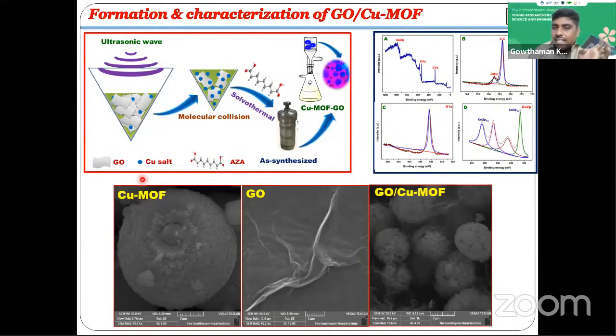We take graphene oxide and copper salt. There is a formation of copper metal ions on the graphene sheets, and then solvothermal reaction with azelaic acid gives the copper MOF on the graphene oxide surface. Why do we need graphene oxide?